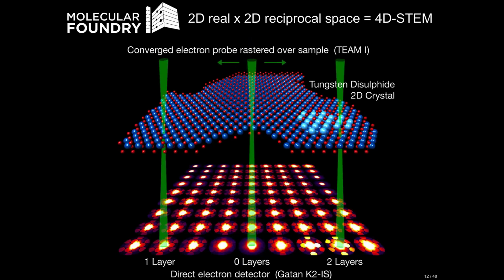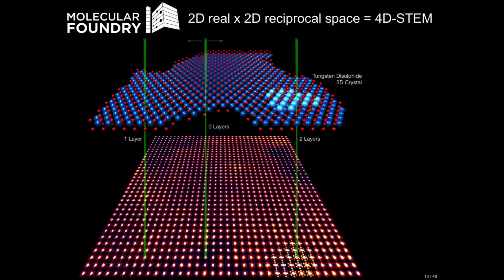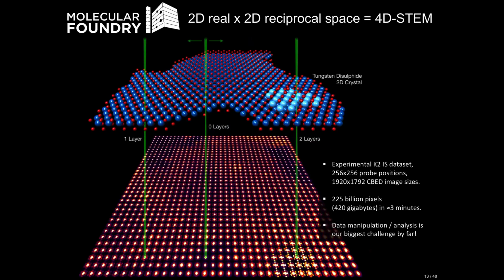Each one of these diffraction patterns is an average of hundreds and hundreds of adjacent diffraction patterns. The reality looks a little bit more like this, and even this is still a ridiculous oversimplification. Each one of these diffraction patterns is an average of 7 by 7 diffraction patterns, so 49 diffraction patterns. That means the experimental data set for this one is 256 by 256 probe positions, and this is on the K2IS camera, so every single one of these images is 1920 by 1792 pixels. This forms a four-dimensional data set that's just over 420 gigabytes of information, and it requires about 3 minutes to record on this camera. So as you can imagine, data manipulation and pre-processing, processing, and post-processing is the biggest challenge for these experiments.